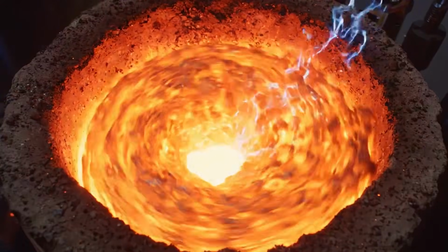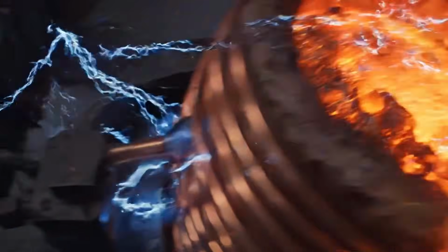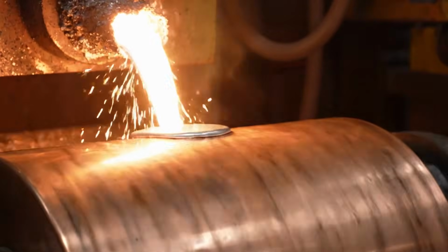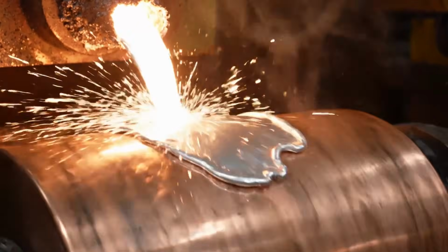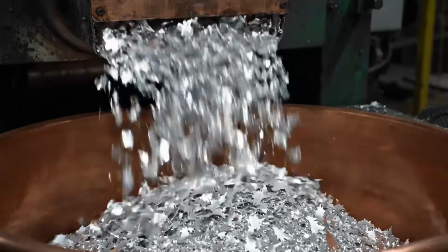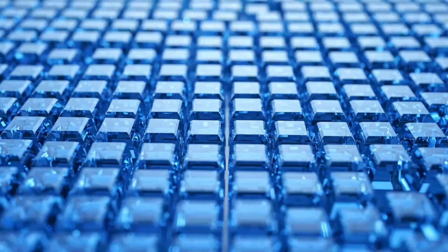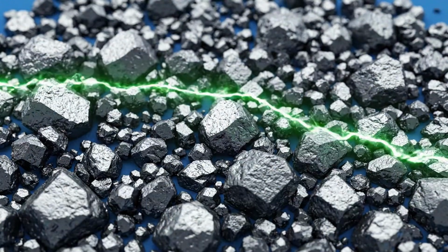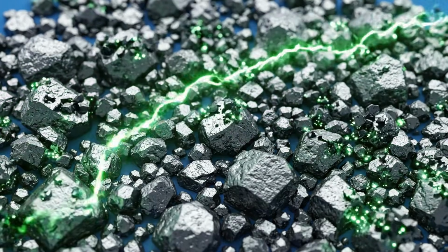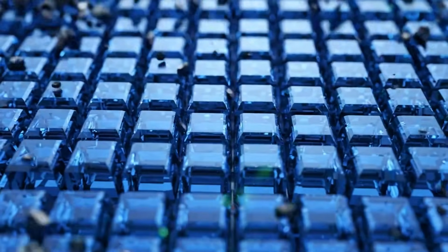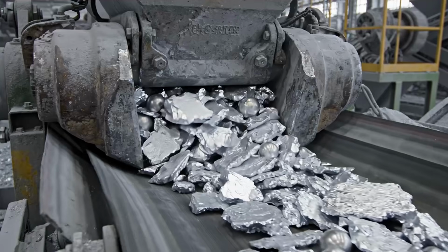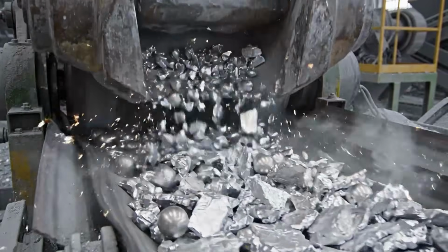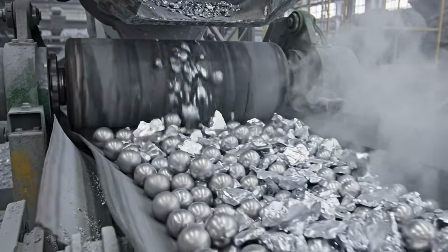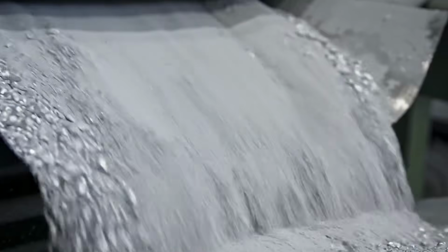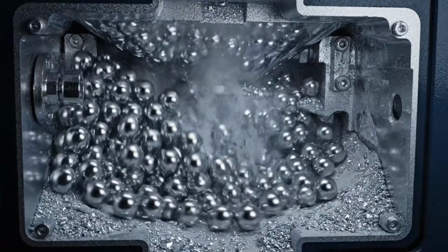Sintering can last several hours. The temperature, time, and cooling rate determine the final microstructure. If the temperature is insufficient, the particles do not bond well, and the magnet remains weak or porous. If it is excessive, the grains grow too large and the material loses performance. The factory monitors this stage with sensors, programmed thermal curves, and recording systems that verify each batch. In mass production, precisely replicating the same thermal curve is as important as achieving the correct temperature.